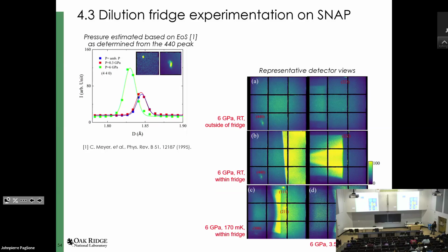So here you see some of the diffraction data as we got them on the SNAP beamline. Based on one of the diffraction peaks, we think that the pressure can be estimated to be 6 GPa, but we are still revisiting this because this is just based on one peak, and obviously you do want to use more than just one peak to get the pressure. But here's just an example of how the background situation gets worse once we added the dilution refrigerator.